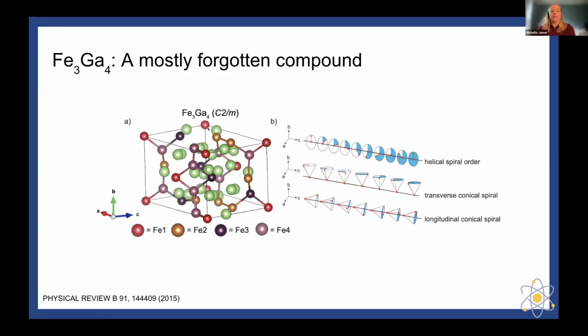So in this work, this is the iron 3 gallium 4 lattice, and it's a monoclinic structure with 4 unique iron sites. The work that was published in 2015 by a group in Louisiana started to bring in some single crystals in order to study what the actual magnetic structure is. As you can see on the right-hand side of the slide, due to the multiple iron sites, the spins can behave differently along each crystallographic axis of the monoclinic structure. So the helical spin spiral is almost like a two-dimensional spin. The transverse conical spiral is whenever it's rotating and precessing around almost like a cone. And similarly, the longitudinal spin spiral structure is like a cone, but in the opposite direction. So we're going to be looking at these 3 different states of the magnetic spins as a function of temperature and as a function of field.